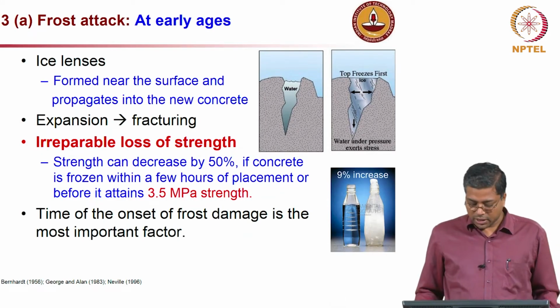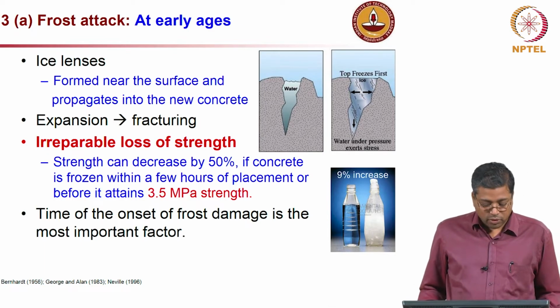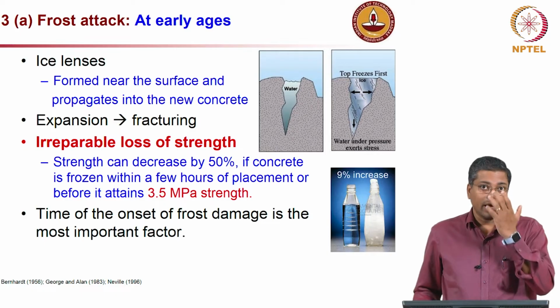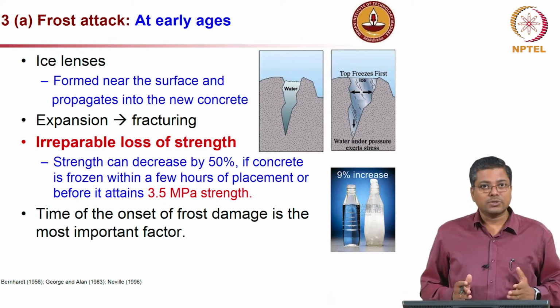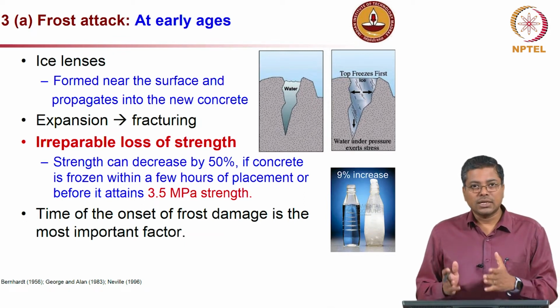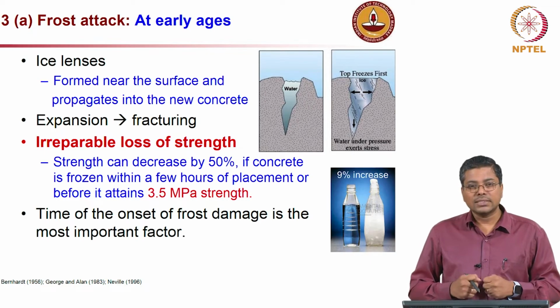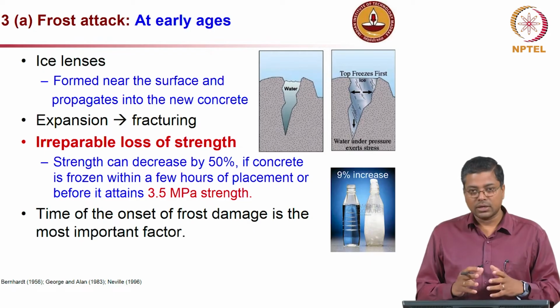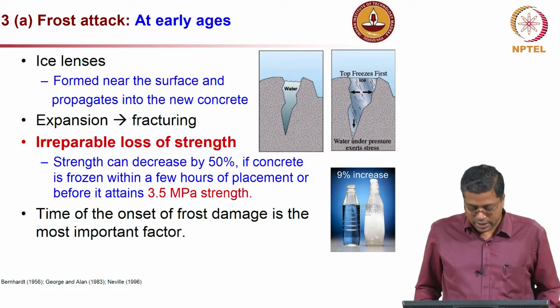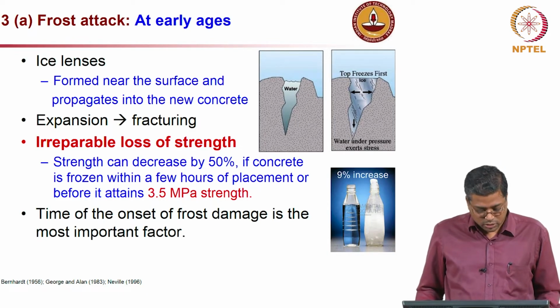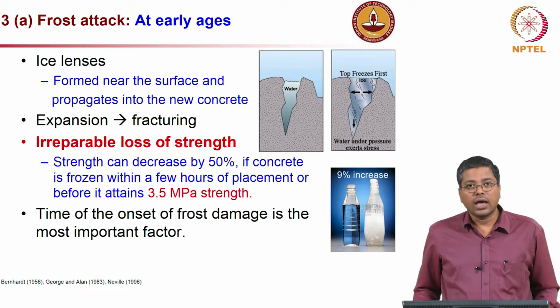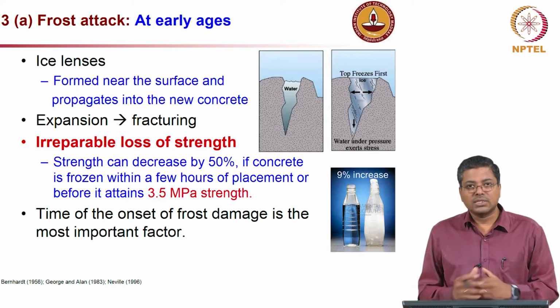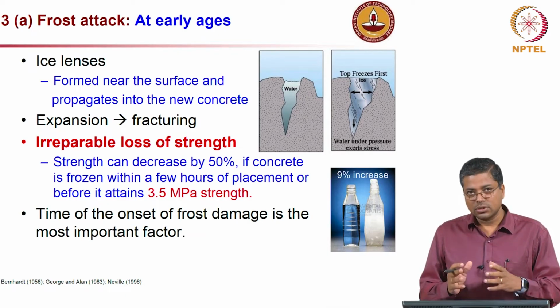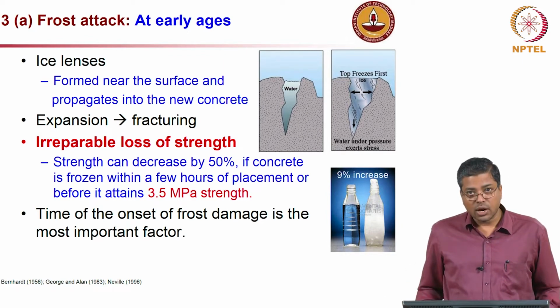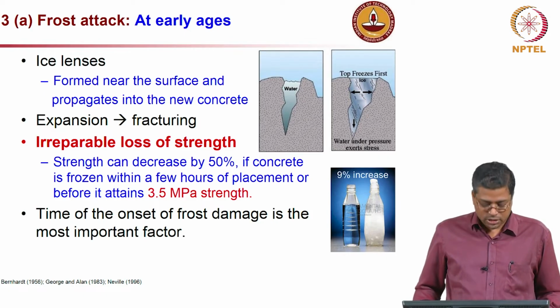So, let us see some more details of this frost attack, which happens mainly at early ages. Ice lenses are formed, or ice is formed at the surface of the concrete first, and then as it expands, like you see in the picture on the top right, a wedge-like ice is formed, and as it expands it pushes into the interior concrete, leading to cracking. Essentially they end up fracturing the concrete, and this can happen in the fresh state itself. When this happens, the mixing water is consumed, it becomes ice, and so sufficient water is sometimes not available for the hydration reaction also.